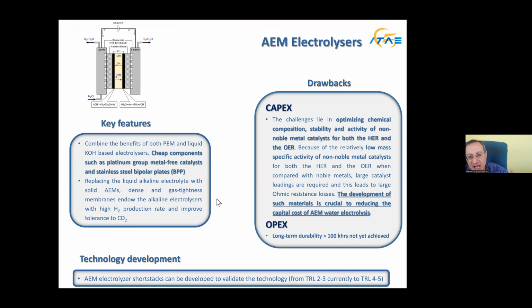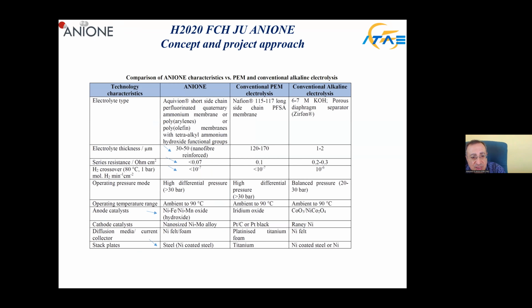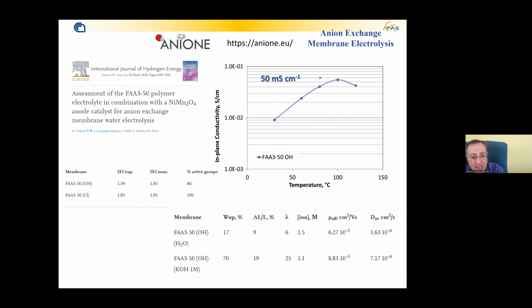To address this, we are now moving little by little to AEM electrolysis technology, which is similar to PEM but operates in an alkaline environment and doesn't use any critical raw material. As shown here, the anion exchange membrane can be reinforced, we have a high differential pressure, nickel iron and nickel manganese oxides as electrodes, and steel instead of titanium. So we have cheap materials. Of course, we have lower conductivity for the anion exchange membrane compared to PEM, 50 millisiemens compared to 200, which means lower performance.